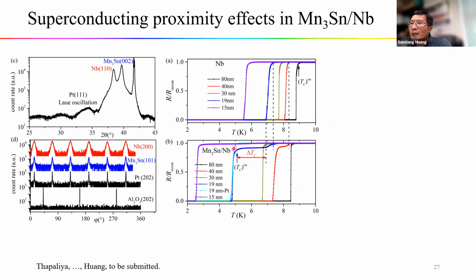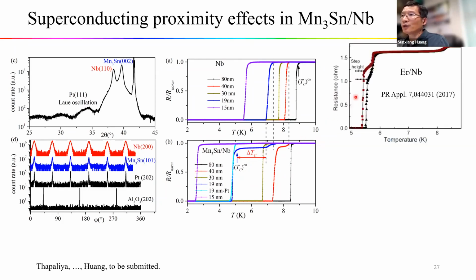Interestingly, we also observe this step-like feature in the bilayer. We are not quite sure what the reason is yet, but this feature has also been observed in the heterostructure between niobium and ferromagnetic helical magnets, such as this ER. One reason could be that there's some magnetically inactive region, so that there is no proximity effect. But another possible reason is the interaction between the Cooper pair and these helical spin structures.